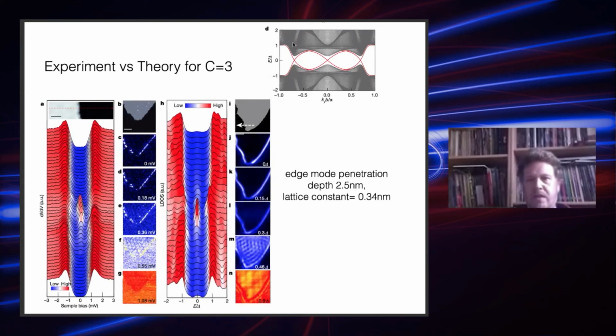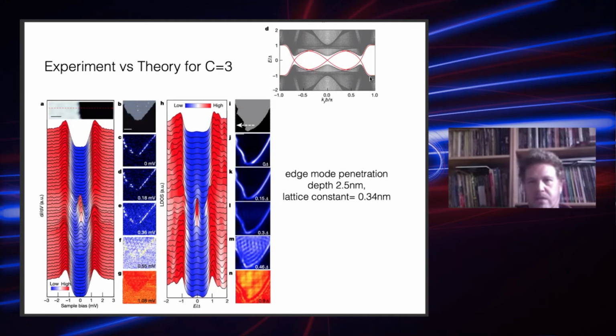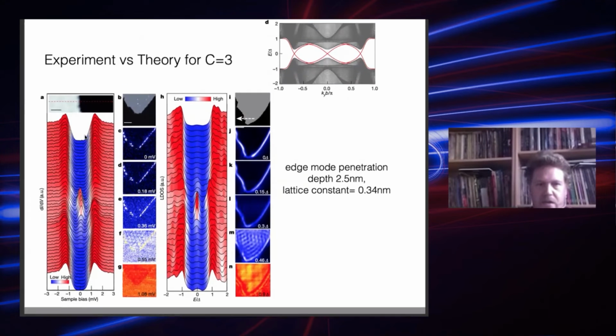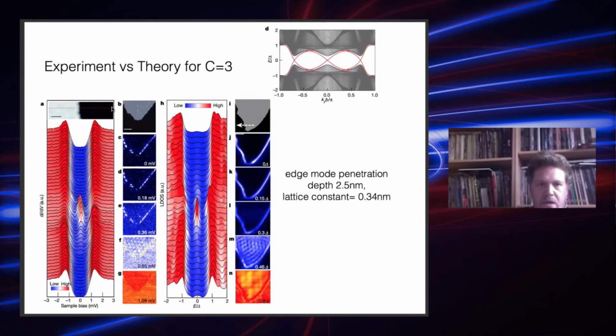So the band structure of this chiral superconductor at C equals 3 would look like this. There are 3 pairs of chiral edge modes in the topological gap. And when we do this dI/dV comparison, moving from the island towards the pristine system, crossing the boundary, the experimentalists see this type of a zero or in-gap structure of the dI/dV.